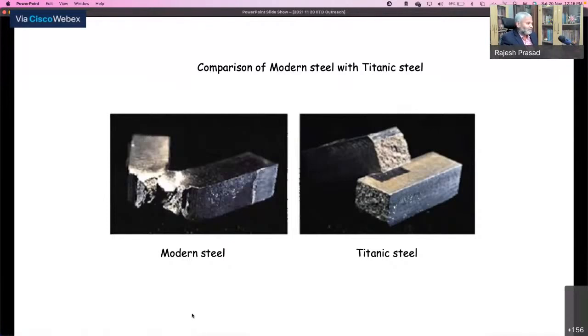In fact, people went down and fetched Titanic steel for testing in the lab. You can see that there was an impact test done, and the modern steel, although it fractured, did not actually break in two. There is still some connectivity, and there was a lot of deformation, plastic deformation. So it was showing a sort of ductile behavior. But the Titanic steel under the same condition, you can see that it just broke in two pieces with not much plastic deformation. So it was actually showing brittleness.